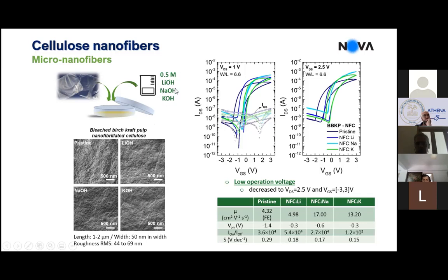This has several effects, to improve the ionic conductivity and ionic mobility within these membranes. You see that this is no longer conventional paper, because the fibers are smaller than the wavelength of the light and they tend to become transparent. You reduce the scattering of light. But what is more important is that if you use this type of membranes to make the devices, the transistors, you see that the hysteresis is now reduced because we are at a much smaller scale. And the operation of these devices, in terms of voltage window, was also reduced by 10 times compared to the previous one that I've shown.